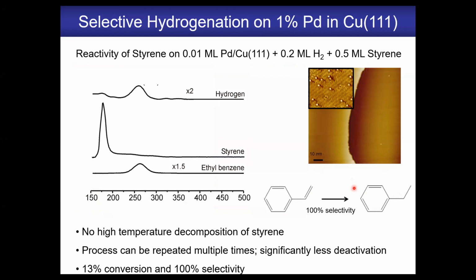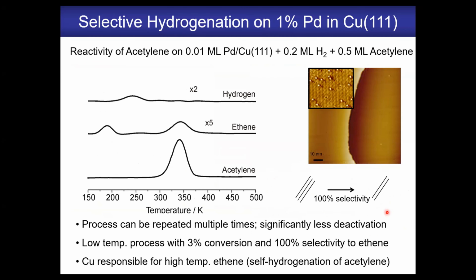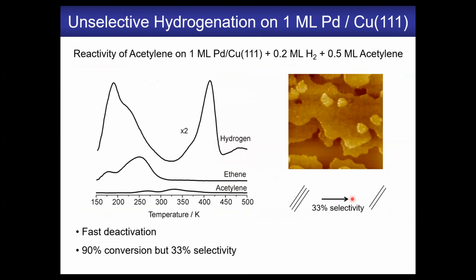And then we can test the reactivity by, this is just a model reaction trying to hydrogenate styrene to make ethyl benzene. And we see that on the single atom alloy surface, we get 100% selectivity to the ethyl benzene. Another example is for a more relevant reaction, hydrogenating acetylene to make ethene. It's 100% selective, whereas if you do the same reaction on a surface that contains a monolayer or two of palladium, as seen here in the STM, you only get 33% selectivity to ethene. You get all this high temperature hydrogen, which means that you've left carbon behind on the surface and decomposed the molecule you've tried to hydrogenate.